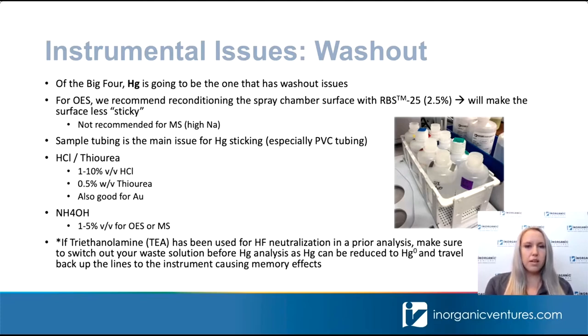Another thing that we recommend for ICP-OES is reconditioning your spray chamber with RBS-25. We use a 2.5% by volume solution. What this is going to do is condition those surfaces and make them less sticky, and result in less washout or less time to wash out. We don't recommend using this for mass spec just because of the really high sodium content of RBS-25. So make sure you're not using that on mass spec, because that can cause a whole lot more issues than your washout concern.